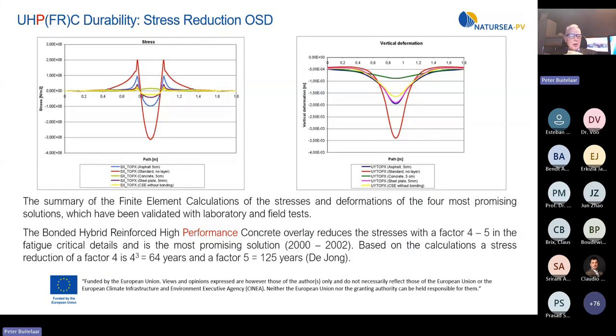Also, the stress reduction by applying a thin bonded hybrid reinforced UHPC on the orthotropic steel decks showed an impressive service life extension up to 125 years. The predictions were not only proven in the laboratory, but also on actual products where the bridges were monitored.